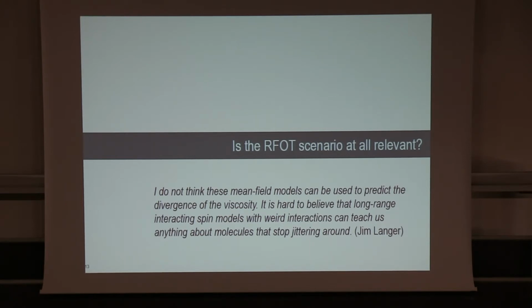Well, in the end, this random field or random first-order transition scenario, which, as I said, I think is beautiful from a mathematical point of view and seems to have a lot of what's needed to build a first-principle theory of glasses. Is it relevant at all for experiments? And this view is still shared by some people on the planet, and in particular, Jim Langer said, I don't think that these mean field models can be used to predict the divergence of the viscosity of glasses. It's hard to believe that long-range interacting spin models with weird interactions, p-spins, can teach us anything about molecules that stop jittering around.